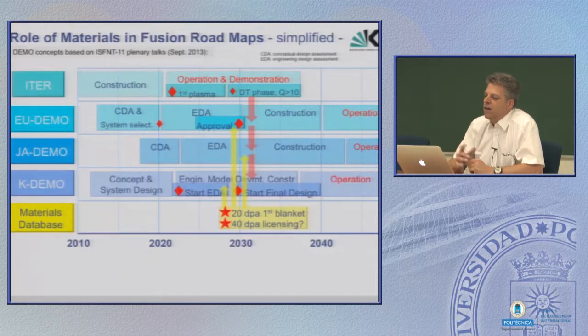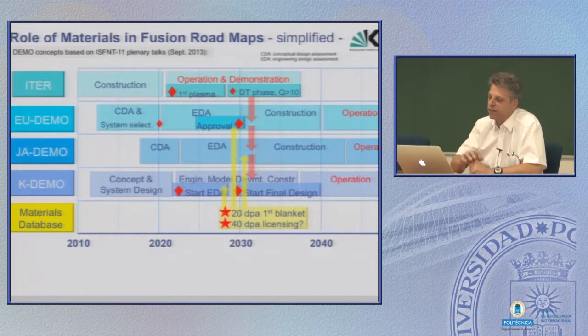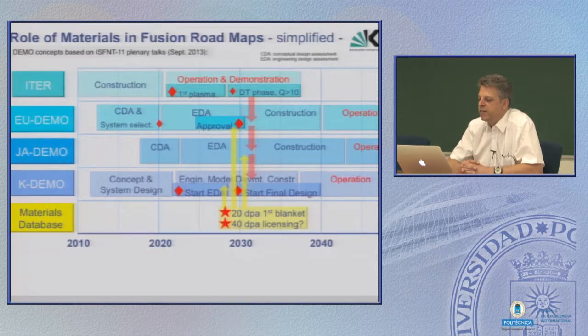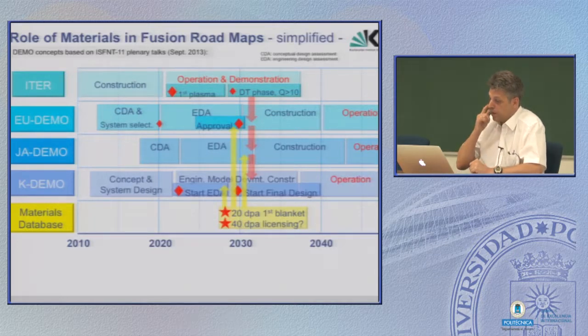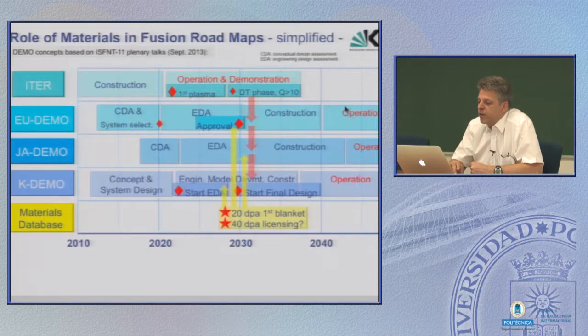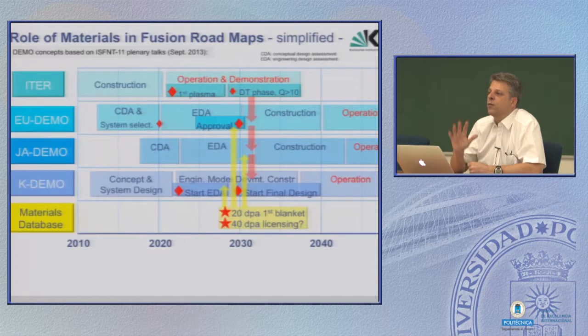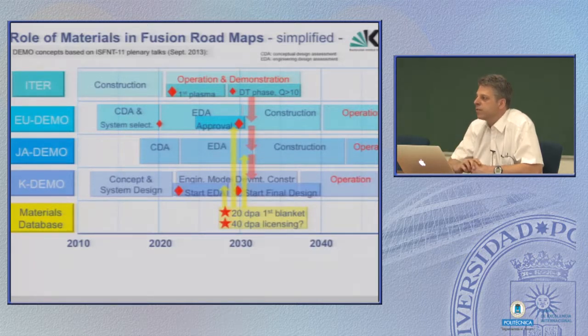But in a demo reactor, we have to produce power, and lots of power, and this means the neutron irradiation will be much higher. And to have a start, I will also go into details later on, very conservatively, which means the first blanket in the European demo reactor will only see 20 dpa. That's a relative term, but as said yesterday, at 20 dpa we are relatively safe with 9% chromium steels. A second blanket is foreseen to be operated up to 40 dpa, which is quite at the border where helium transmutation effects come into play. But still, the European demo program is a rather conservative thing.